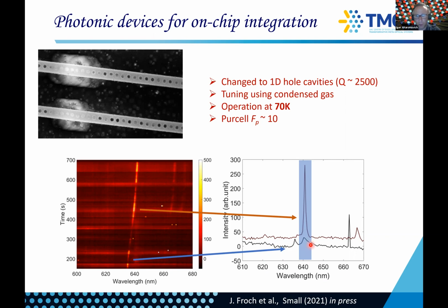And you can see, so this is cavity and emitter, and this is cavity and emitter on resonance. So with a Q of about 2500, we can already see a Purcell effect of about 10. And I guess one remarkable thing is we're doing this experiment at 70 Kelvin.